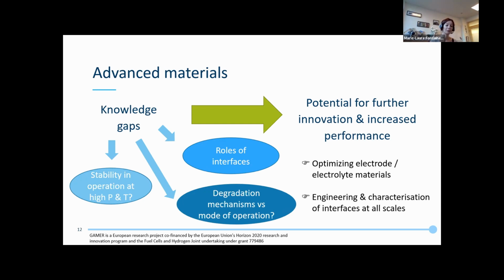Within 800 hours, we have seen we are within the frame of this degradation rate, and this degradation in our case is mostly associated with evolution of the current collection interface with our electrode. So I would not ascribe it completely to material deterioration, but we have a problem with keeping contacts because of this tubular technology.